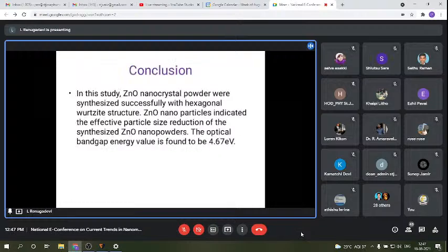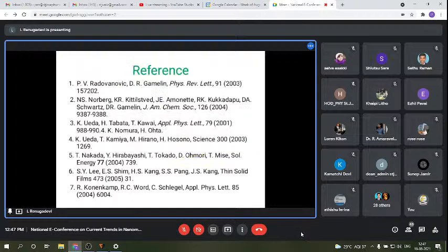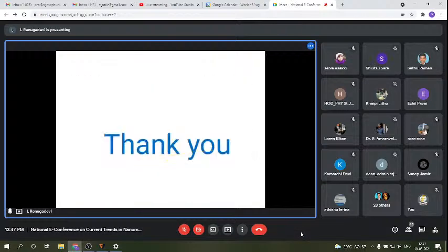Then conclusion, in this study, we have synthesized pure ZnO nanoparticle successfully by the solvothermal method, and its particle size has been reduced. The optical band gap energy value was found to be 4.67 electron volt. These are the references of my manuscript. Thank you.